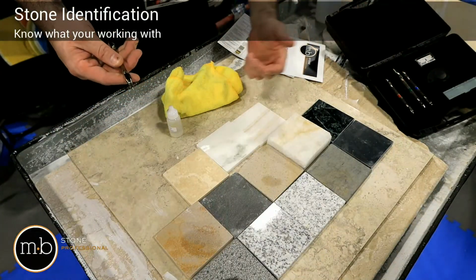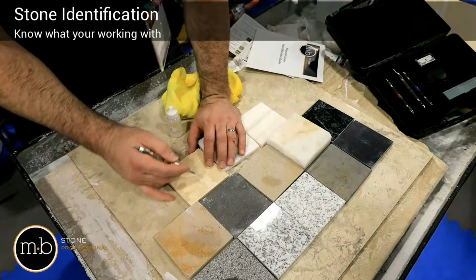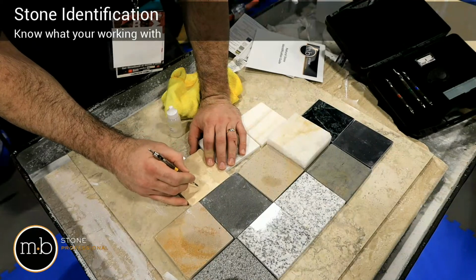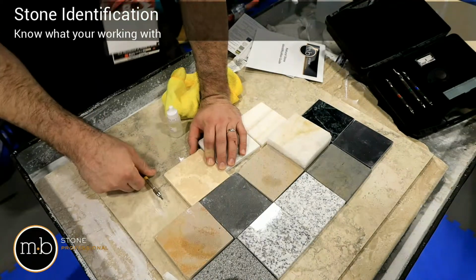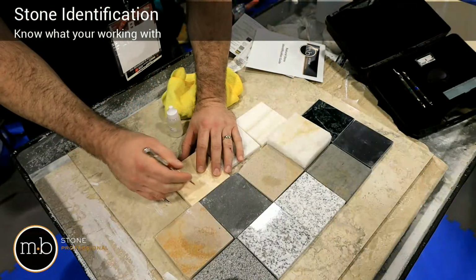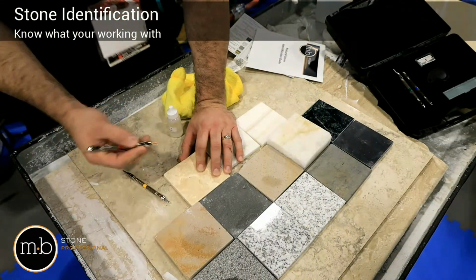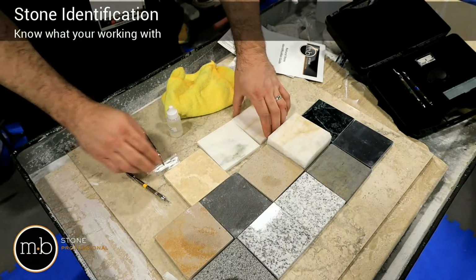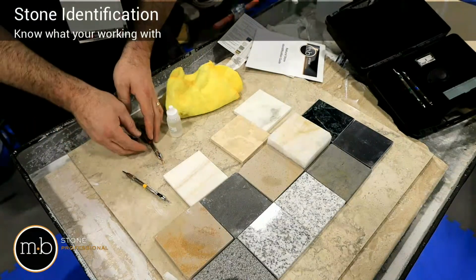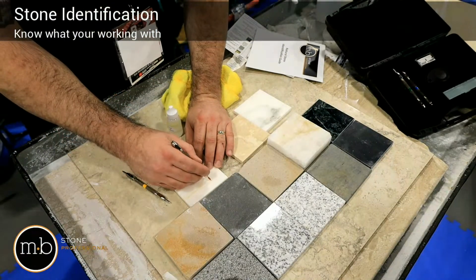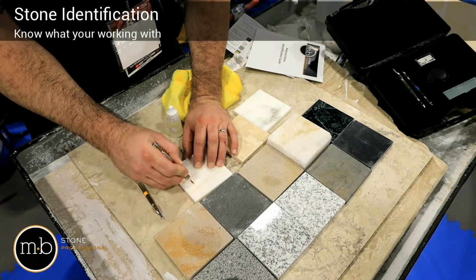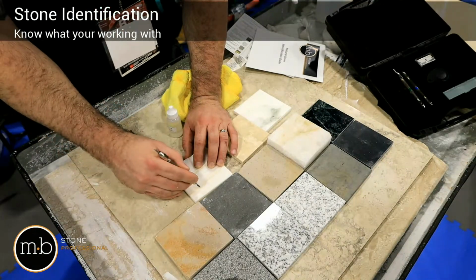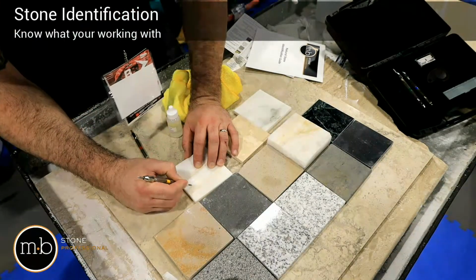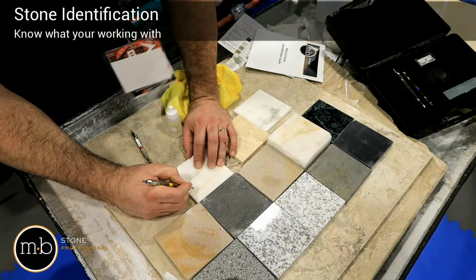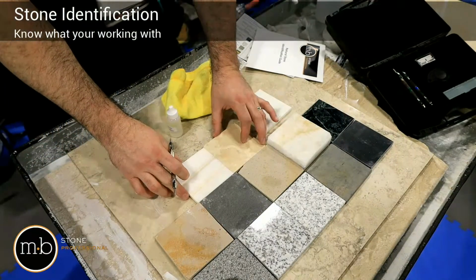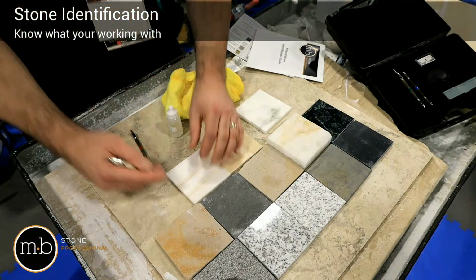So something like travertine, everybody knows this by visual identification, but a number 4 scratches the travertine. A number 3 does not. Onyx does not scratch with a number 3. And it's actually barely leaving a mark with number 4. But I would say that's a hard 4. 5 should definitely leave a mark.